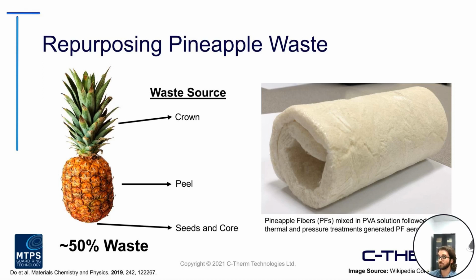So in an attempt to reduce some of that waste, this group took these pineapple fibers, known as PFs, they mixed them with a PVA solution, did some varying thermal and pressurized treatment, and essentially created these aerogel blankets that you can see rolled up on the right there.